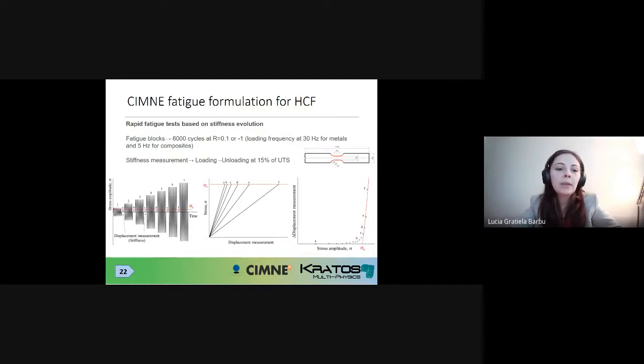So in the Fatigue for Light project that we have in our group, we've worked together with Eurecat and with ArcelorMittal to design a testing strategy which significantly lowers the experimental time needed for fatigue experimental characterization. They have developed at Eurecat a rapid fatigue test, which is based on stiffness evolution. What does this consist of? Well, they apply blocks of cyclic loading of 6,000 cycles specifically, either at a ratio of 0.1 or at a ratio of -1, with a specific loading frequency depending on the material.